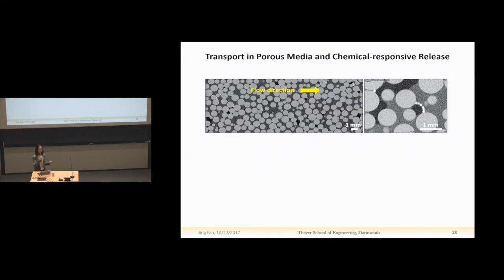We inject 10 pore volumes of water to recover most of the oil. So what is left in the column is some trapped oil blobs, and they cannot move anymore. And then we inject the suspension of capsules in water into this porous medium. And we use micro-CT to visualize different phases inside.